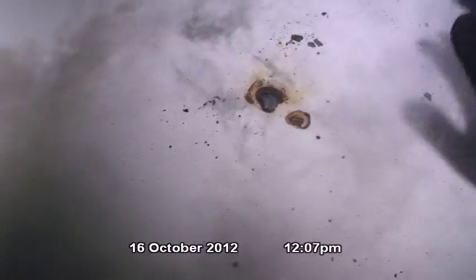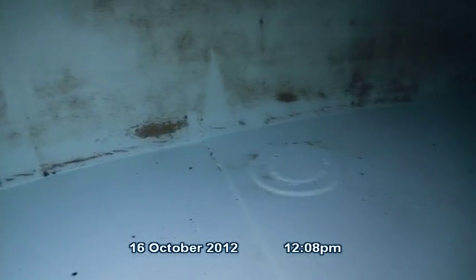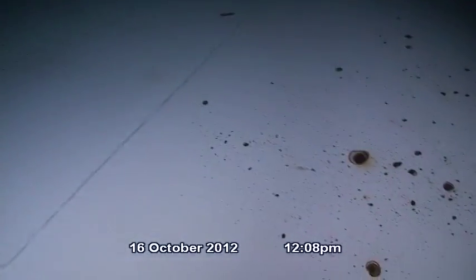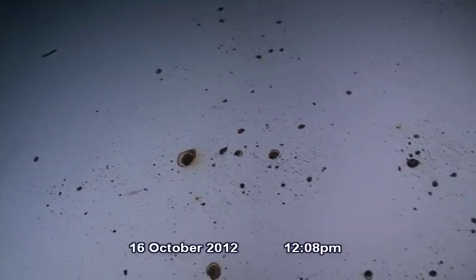The diver has removed the corrosion nodule to check for any pitting or metal loss. Moderate metal loss is taking place in this location. The epoxy coating on the floor is slightly chalky and would break down with contact by the diver's gloved hand. Coating defects have resulted in corrosion ranging from pinhole type corrosion to moderate corrosion in thousands of areas on the floor. All the loose sediment and debris has been removed from this area.